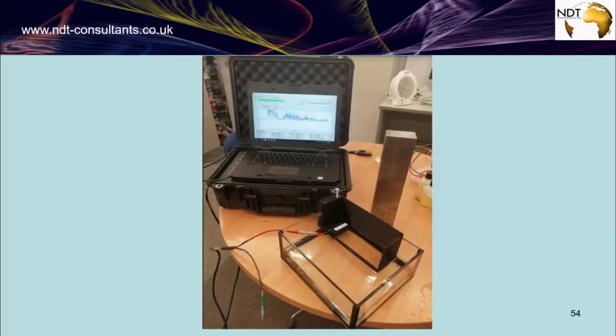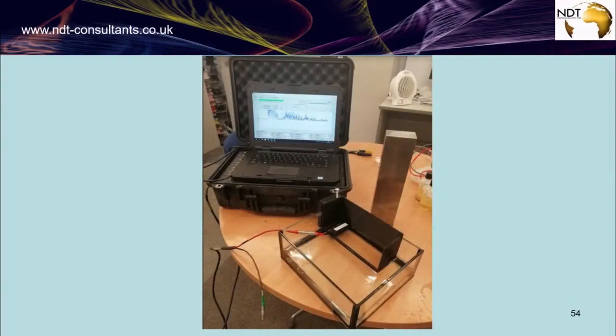So we designed and manufactured some ultrasonic transducers, and as you can see in this picture, this big black box is the power supply, and this container there contains the solvent, where we put the electrode material in the liquid, and the small black box with the white sticker is the transducer that we developed. So that will create cavitation or ultrasound, and this will delaminate the active material from the electrode.